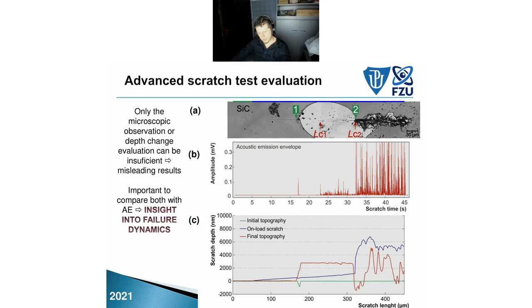There's just a small notch, and the coating cracks in fact at point 2, and the crack is apparently backwards. So the coating cracked backwards and is delaminated, which we can see from the final topography. The acoustic emission gives another insight and reveals what happened. The acoustic emission during onload shows that there is some signal, apparently the breakage of an asperity, probably. There was probably some asperity that was deposited during the deposition process and embedded into the coating itself. And nothing here. And there is some small signal, some small cracking, which was apparently the cracking of the substrate below the coating itself.